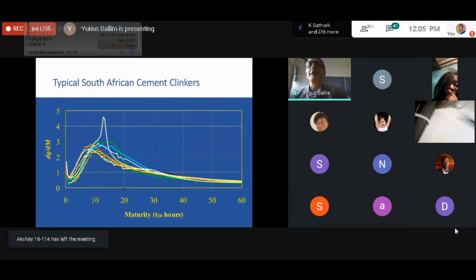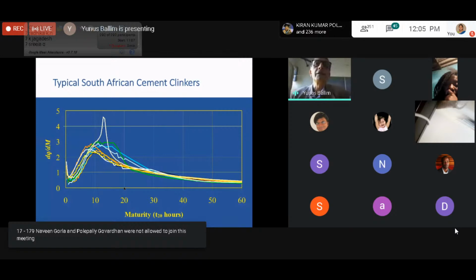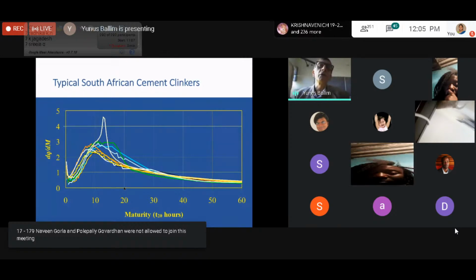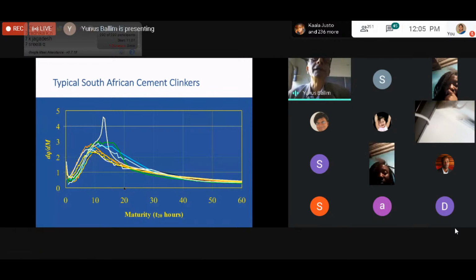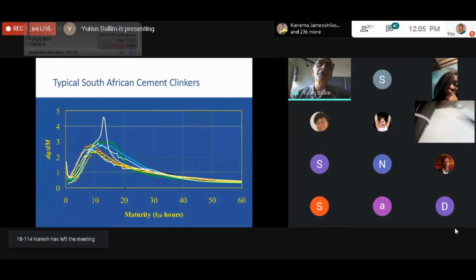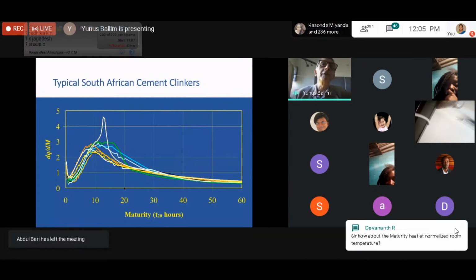This is just maturity heat rate curves for typical cement. And what I wanted to show you here is that, for those of you who are counting, there are 8 heat rate curves here. And this is 8 cements from 8 different plants in South Africa. They're all sold as Portland cement, but actually they have very different heat rate characteristics.